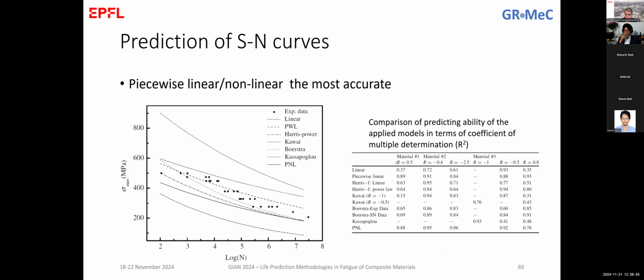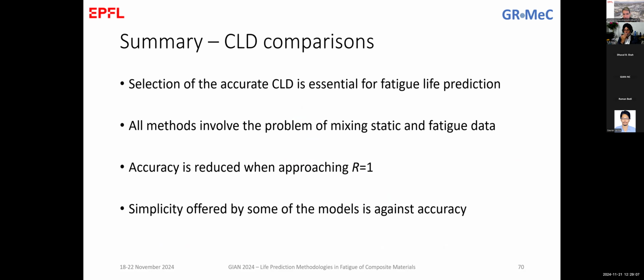So we have another comparison, and then I also gave here the coefficient of correlation, showing again that piecewise linear is stable and can predict with a good accuracy most of the cases that are used. So the summary for CLDs is that the good CLD selection is essential for a good fatigue life prediction. All methods involve the problem of mixing data. Again, the same problem that we have with the SN curves. Either we use the static strength data or not.